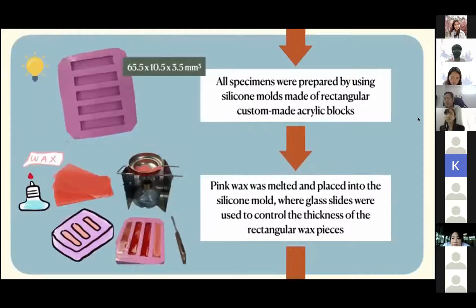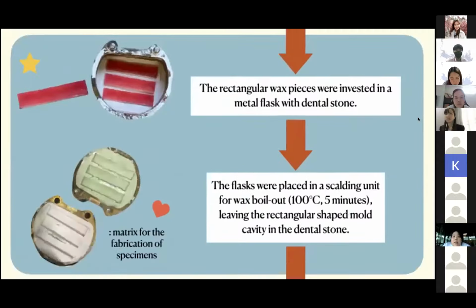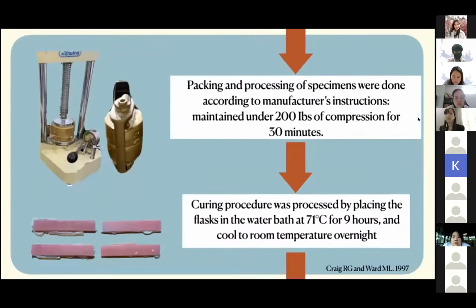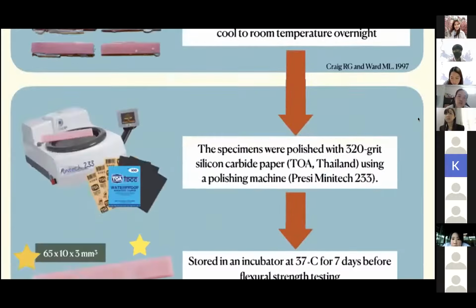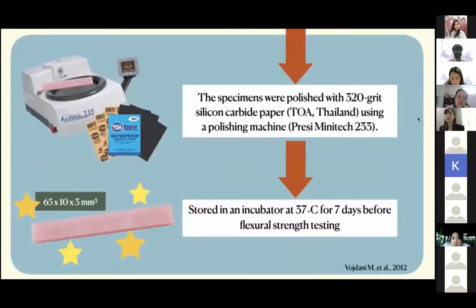Specimens were prepared using silicone molds, and pink wax was melted into the mold using glass slides to control the thickness of the wax pieces. The wax pieces were invested in the flask and boiled out at 100 degrees Celsius for 5 minutes. The specimens were then packed and processed according to the manufacturer's instructions. The specimens were removed from the mold, finished, and polished with 320 grit silicon carbide paper with a polishing machine.